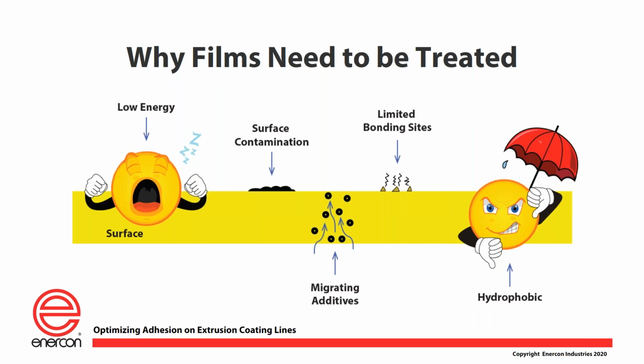In addition, a lot of these poly products have surface contamination. It could just be from storage, it could just be from the air, or it could be from migrating additives that are already baked into the structure of the film. So at the end of the day, what this means is the surface of that product is really not suited to allow for wetting at all. And so we need to treat this surface in order to bring that surface tension back to an area where it will be more receptive to wetting a liquid. Next slide.